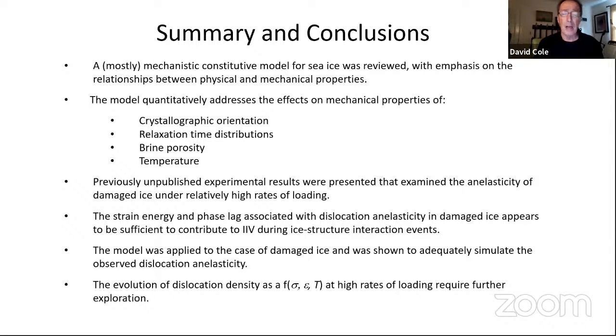So with that, I think there are a few areas if someone were interested in pursuing this mechanism. It's a pretty straightforward but not simple matter to flesh out this dislocation density relationship to stress, strain, and temperature, but at high rates, which I haven't done. That's really the piece that needs to be filled out before you'd have complete confidence in going forward with this mechanism. But all the indications to this point are very encouraging. So with that, I'll end.